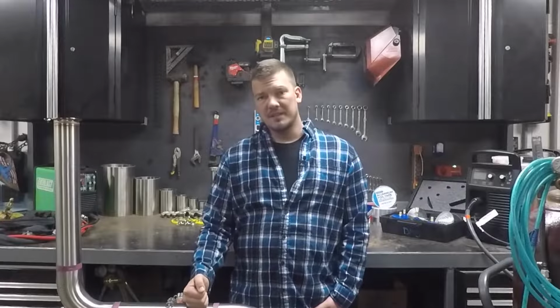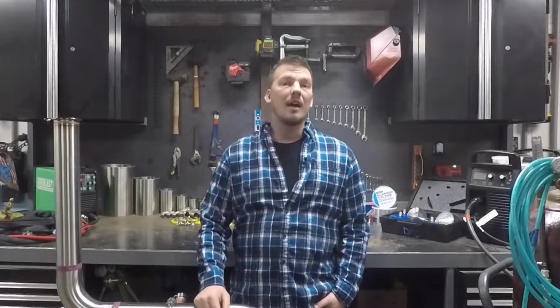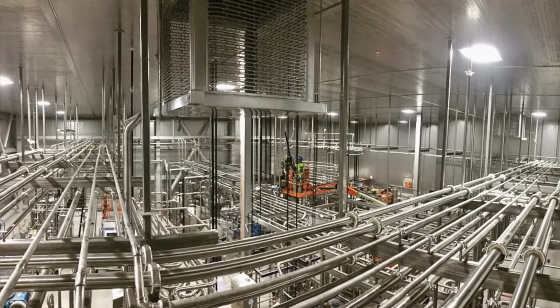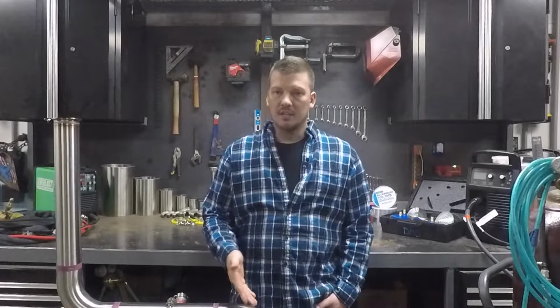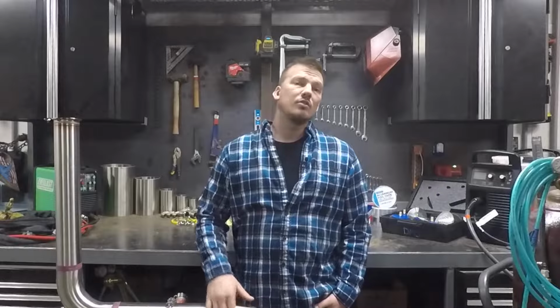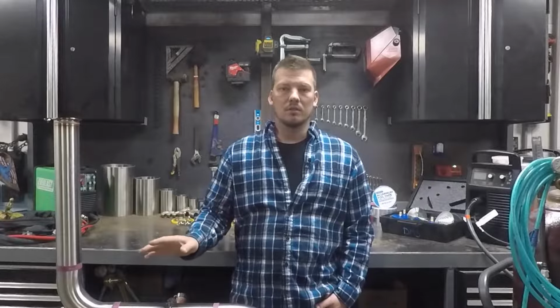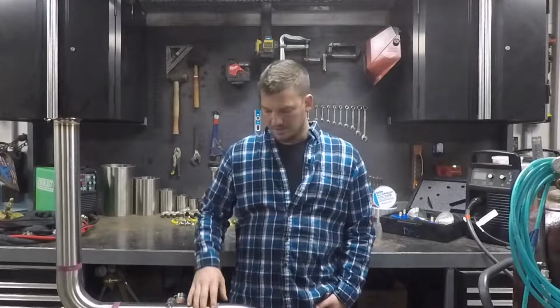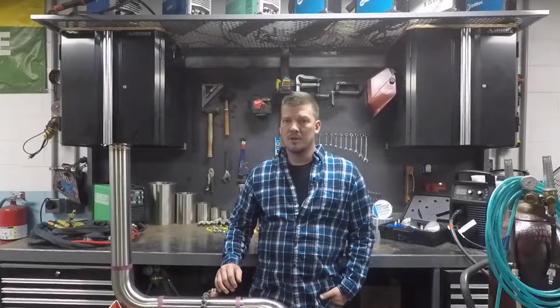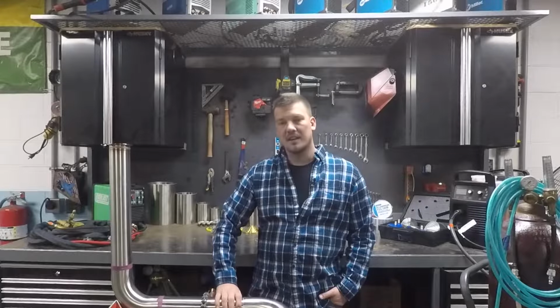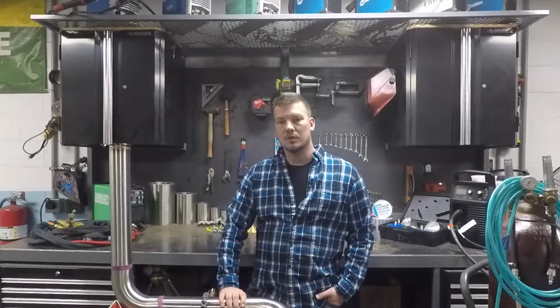Now, whether you're welding a short piece on the bench or an exhaust or a line that runs the whole way across the plant, the principle is the same. Like I said, purging in low, out high. You want to close off every opening or olet along the way, and you want to tape off every weld seam. Because not only does that affect your purge pressure, but even a weld seam can suck in enough oxygen to color or sugar a weld.